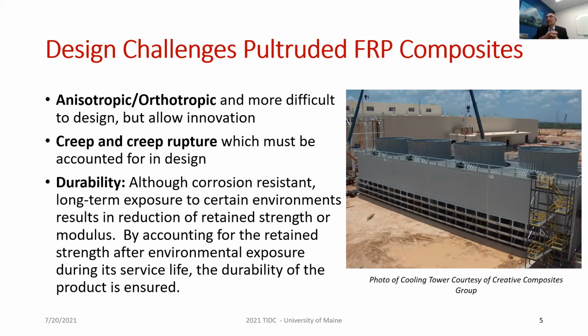There are challenges in the design of pultruded FRP composites due to the anisotropic or orthotropic nature of the material, which makes the job of design difficult but allows innovation. Creep and creep rupture are characteristics of pultruded FRP composites, which are not found in many isotropic homogeneous materials such as steel, or for that matter, concrete. When it comes to durability, although pultruded FRP is not susceptible to corrosion in the way that steel is, it does lose strength to some extent and modulus with exposure to different environments. And this is essentially taken into account by looking at the retained properties.